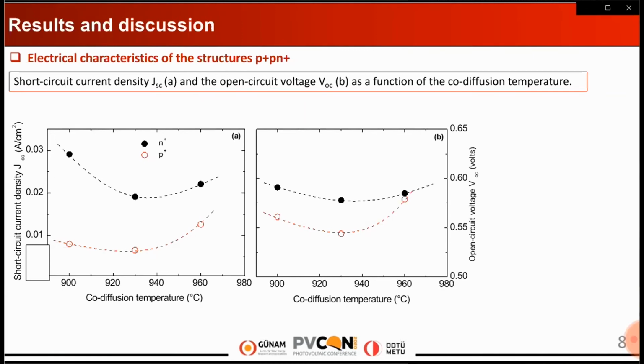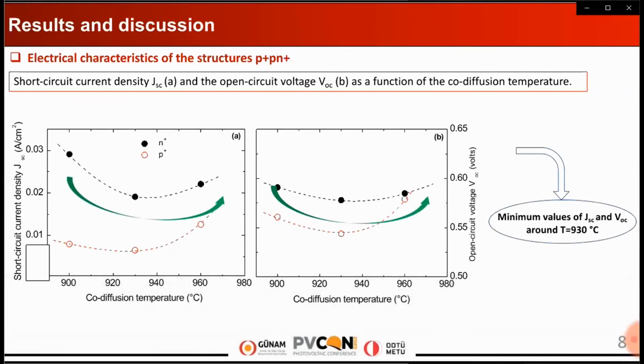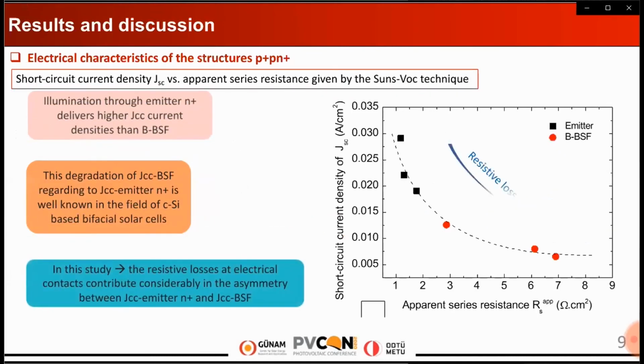So the data shows the presence of a minimum value corresponding to the structures elaborated at 930 degrees. In this study, the degradation of the current density associated to the boron BSF side is mainly due to the resistive losses at the electrical contacts, which have been found very high compared to the losses in the emitter front contacts. So the use of specific silver aluminum alloys proposed by researchers working on these topics is very important in order to decrease the contact resistance with P plus.